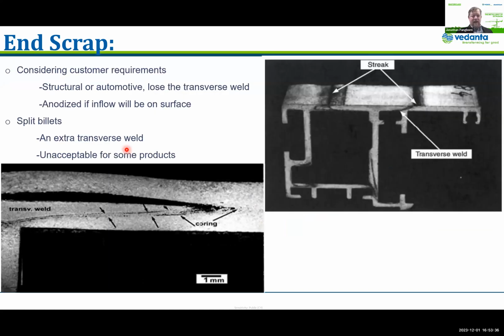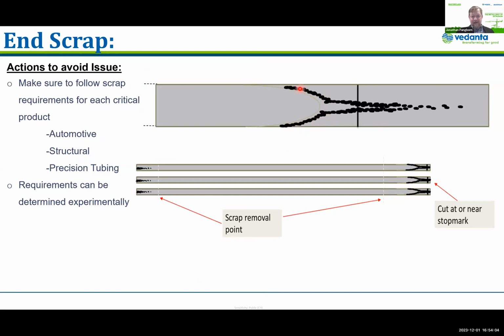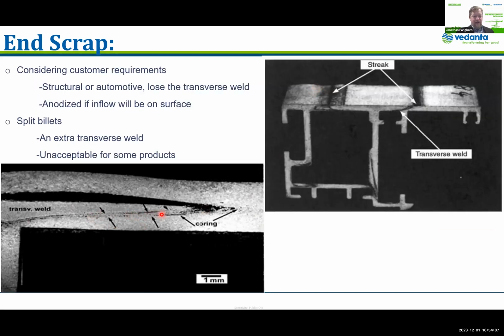Here are some examples around the end scrap, and this is a really interesting one because it actually shows three different things that are related that we've talked about. One is the transverse weld, which really is this inside line that you can see, very clean metal. The first line here is the interface between the two billets. Right outside of that, analogous to what we're talking about here, is the coring, this sort of more fuzzy, dark stuff. And in this case, there's actually a blister associated with this transverse weld at the same time. I don't think this is the same part, but it shows, more macro, some of the similar effects.